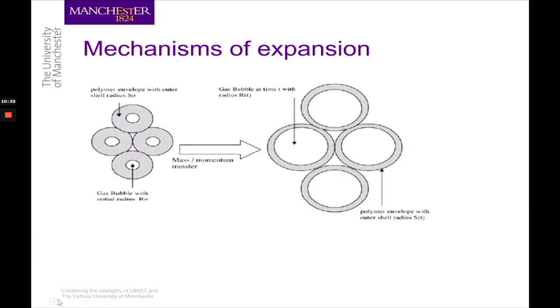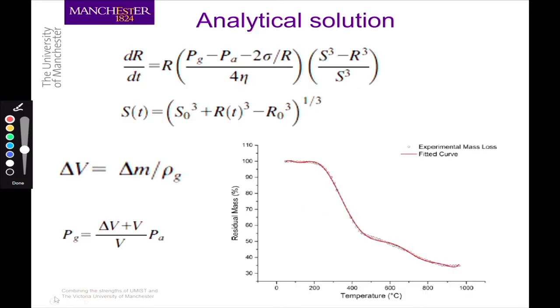How does expansion occur? Well, if you've got a substance which has some gas inside, and the pressure of the gas is increased, then of course it expands to be such a size. That is really the mechanism. And many years ago, a very clever scientist did some research and derived an analytical solution to say how much expansion changes as a function of time, as a function of the pressure of the gas, as well as the surface tension of the bubbles inside. So we adopted this theory in our calculations.